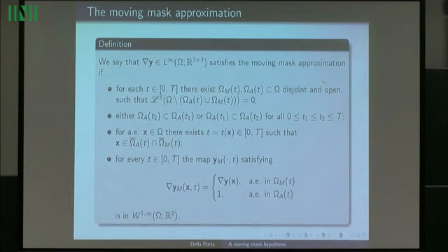we can try to transform this requirement into formulas. As I was saying, the first hypothesis is that we consider two different regions, one occupied by austenite, one occupied by martensite, and we can assume that austenite or martensite is expanding or shrinking. Without loss of generality, you can assume that austenite is shrinking, and we assume that for almost every x there exists a time when the interface passes through this point.